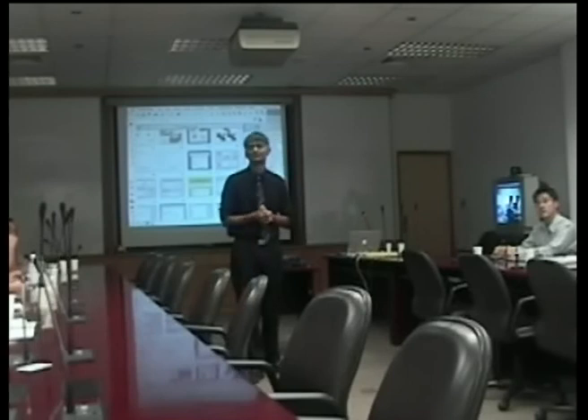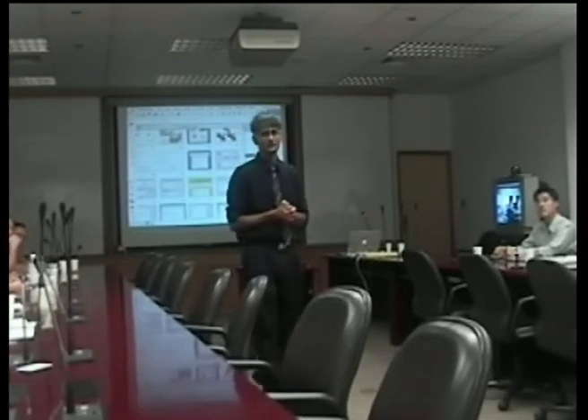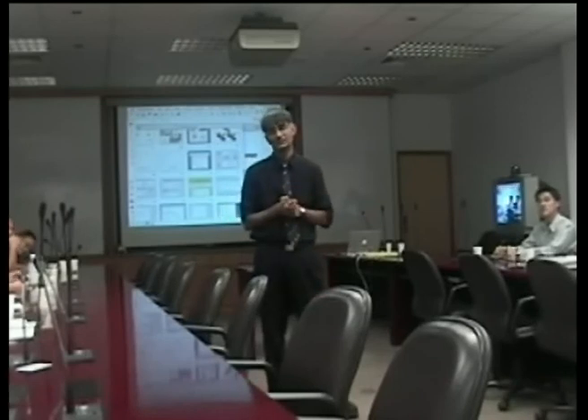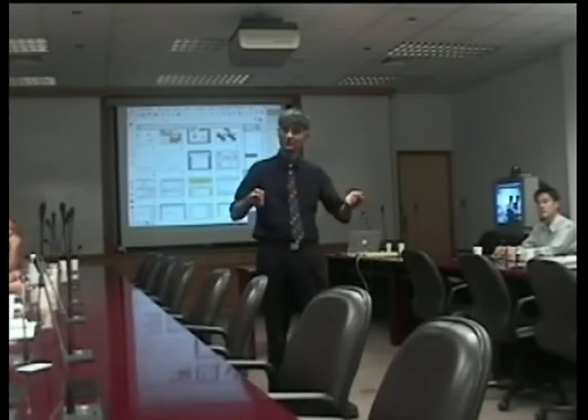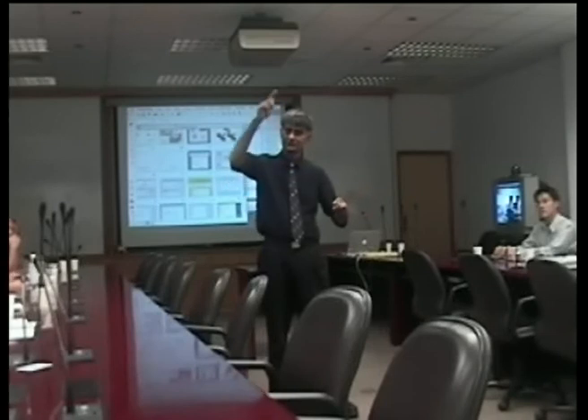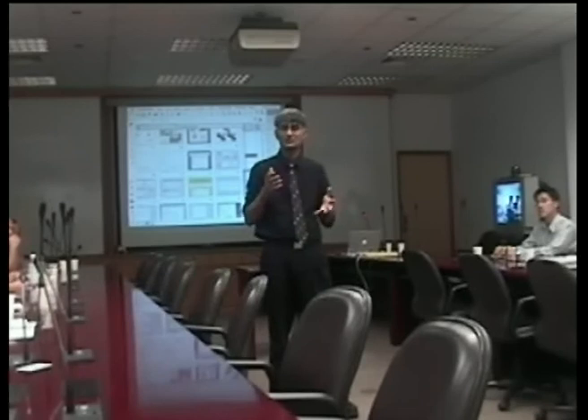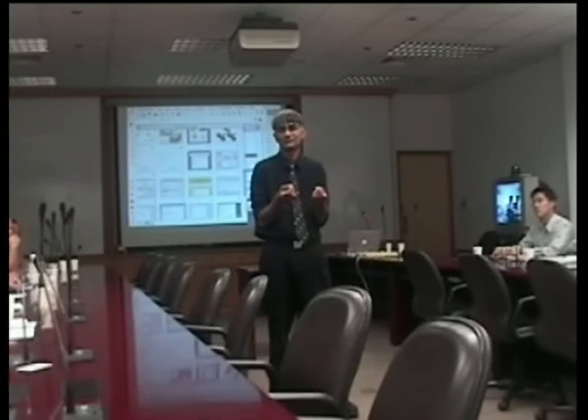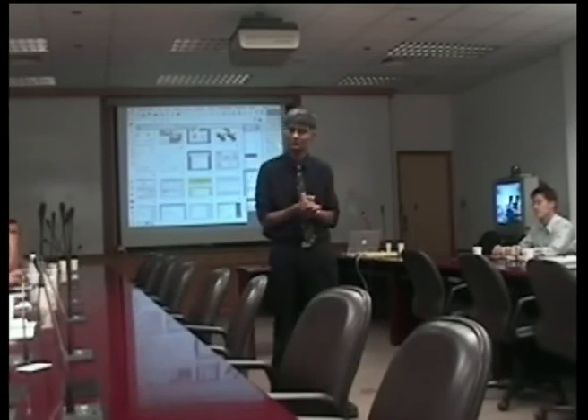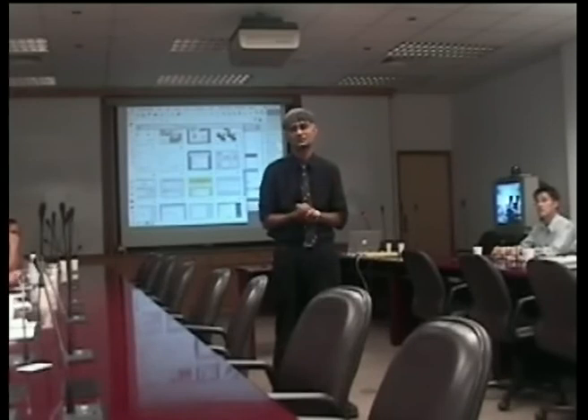Thank you. Is creep sensitive to temperature? I don't think that anybody has studied that. What we have done is a tempering experiment. After the deformation, we temper it at about 300 degrees centigrade. We tried to investigate what that 50% carbon region was, and it didn't disappear after we did a heat treatment at 300 degrees centigrade. So we're still puzzled about what it is, but we have done nothing more than that for temperature sensitivity.